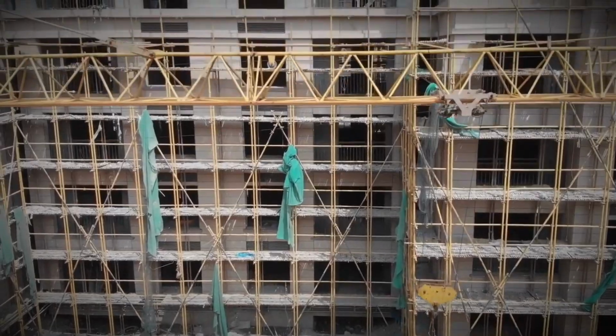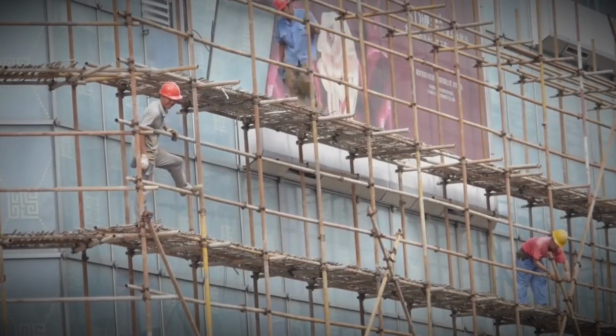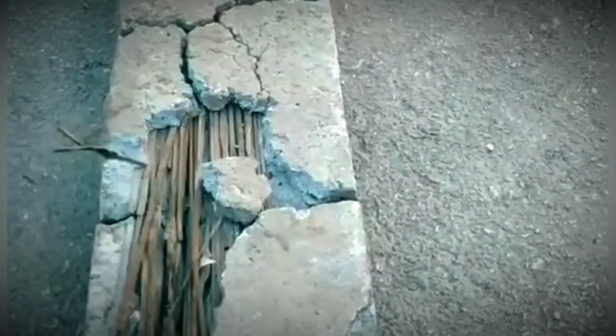The science of why this fails is simple: moisture and biology. Concrete is porous. Over time, water vapor and moisture inevitably seep into the walls. Steel rebar can rust, which is bad, but bamboo rots. As the organic material decays inside the wall, it shrinks, turning into compost. This leaves a void inside the concrete, a hollow tube where the reinforcement used to be. The concrete is now unreinforced and riddled with holes.